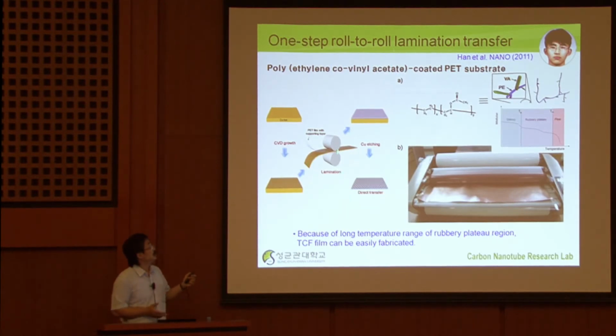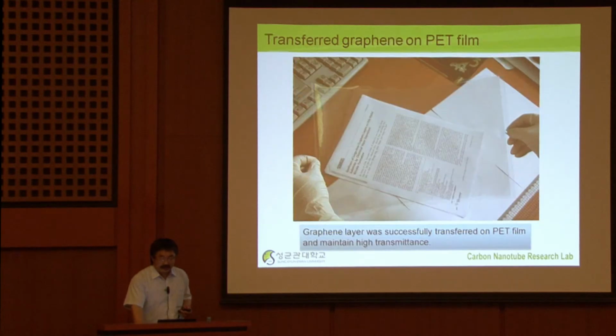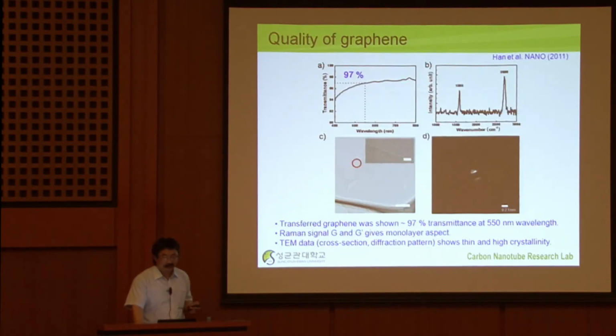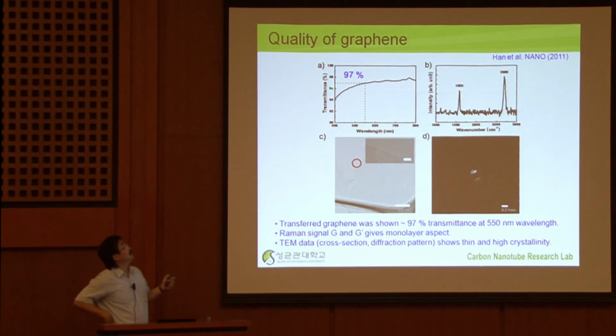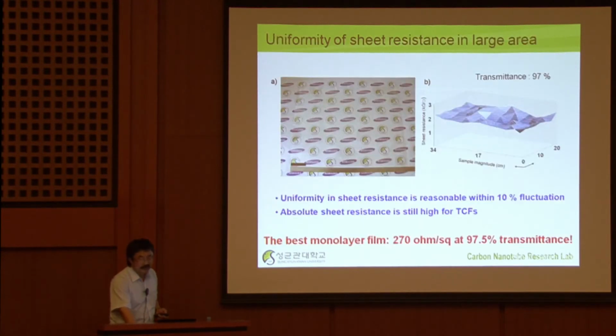So we stick them together, and then we simply dissolve this copper layer by copper etchant. Then you have graphene on PET, which can be used for transparent conducting film. So this is a method people developed. And if you do that, then you can see the transmittance is 97%, which means you have single layer graphene. Another evidence is this Raman spectroscopy here, this G band and G prime band, which is characteristic of single layer. You can also identify them from this TEM and also electron diffraction pattern.